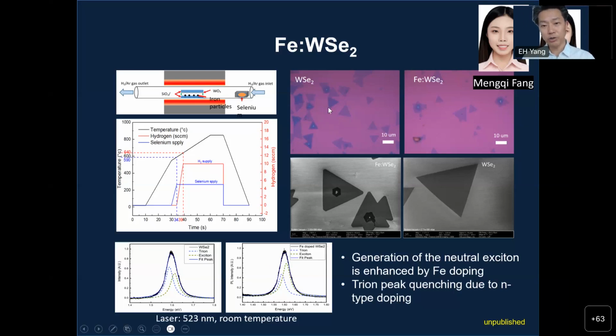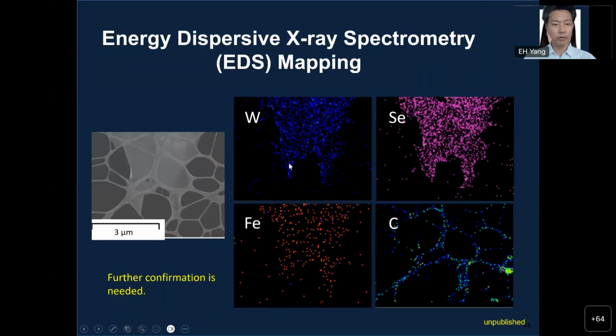On the right, it shows an optical image as well as SEM images of undoped and doped tungsten diselenide. And we performed energy dispersive X-ray spectrometry, EDS, and it's a little controversial, but for now we see these tungsten, selenium, iron and carbon signatures here. But further confirmation is required. But I just decided to show it anyway.